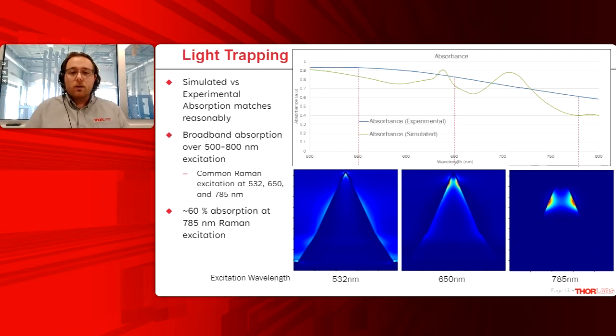This theory was developed using some FDTD simulation tools. So we decided to run some more simulations. And what we found is that this is, in fact, a broadband absorber. The simulations that we've run, we had to simplify them to a single nanopillar, and this was just due to computational efficiency. But what's interesting is that if we look at the frequency domain for different wavelengths of light that are common to Raman excitation, you can see that the electric field is being localized to different heights along the pillar, indicating that there is some credence to this theory. And we're having this broadband light trapping. We are creating this electric field that can be distributed along different heights of the pillar and create this broadband absorption.